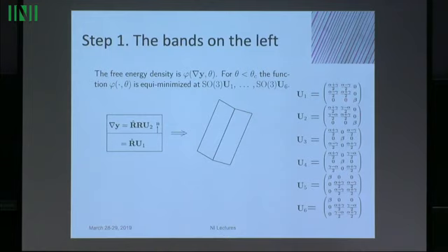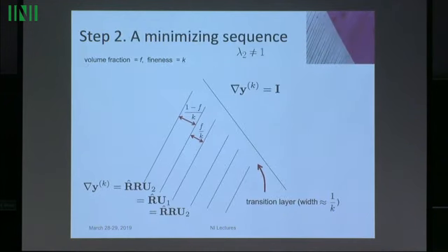And everything's measured, so then you go to this structure. You look at the deformed configuration like I've looked here, and you compare with this picture, and it agrees perfectly, even at atomic scale, it's usually in Cauchy-Born rule. The atoms are in the right positions relative to the interface and so forth. Okay, so that explains, and they have a twin relation, there's twinning and so forth. It doesn't matter so much.